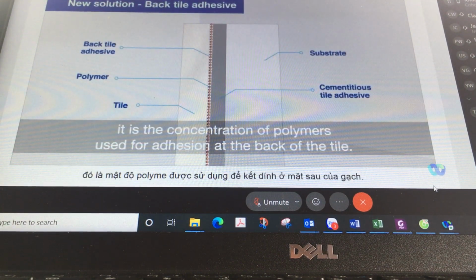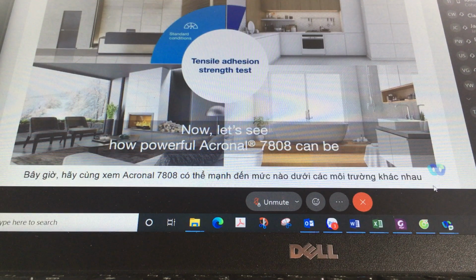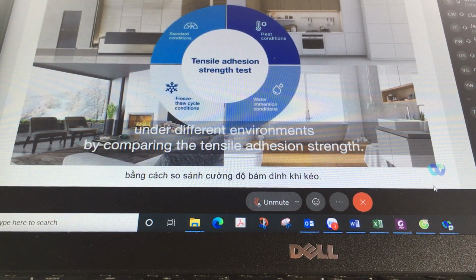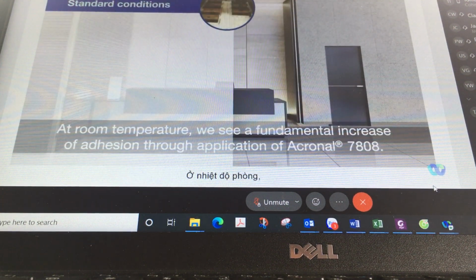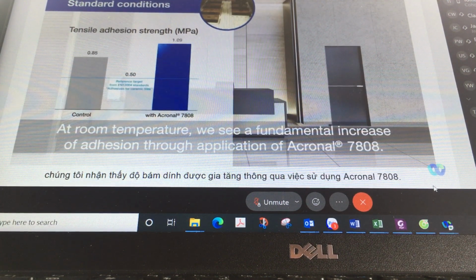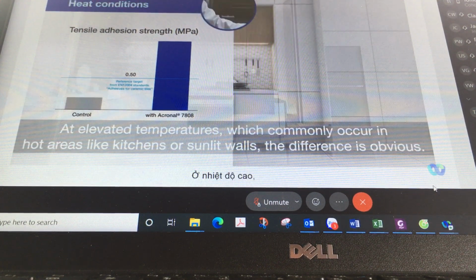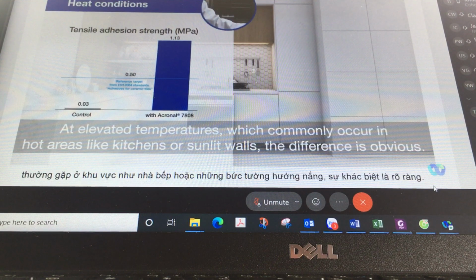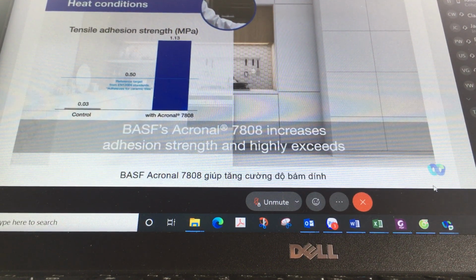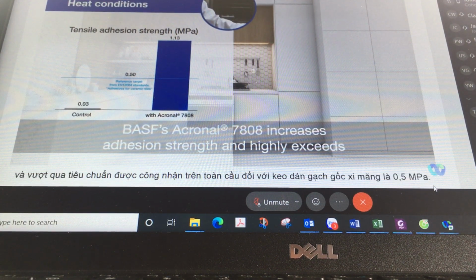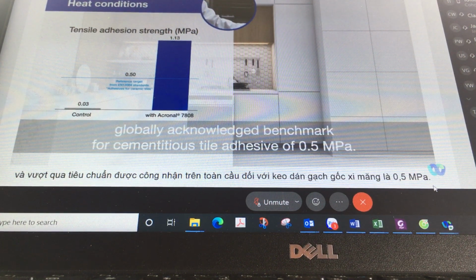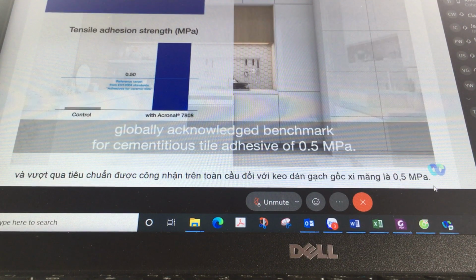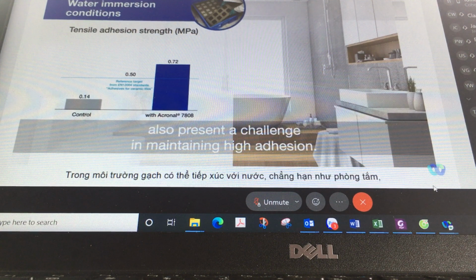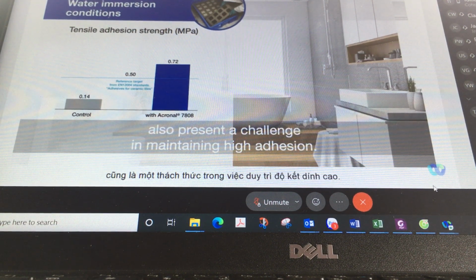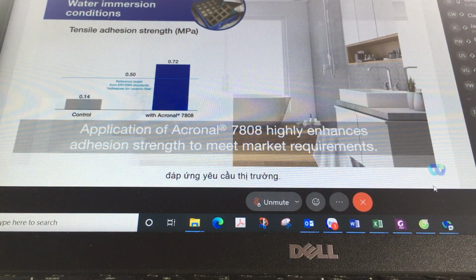As we explained earlier, it is the concentration of polymers used for adhesion at the back of the tile. Now let's see how powerful Acronal® 7808 can be under different environments by comparing the tensile adhesion strength. At room temperature, we see a fundamental increase of adhesion through application of Acronal® 7808. At elevated temperatures, which commonly occur in hot areas like kitchens or sunlit walls, the difference is obvious. BASF's Acronal® 7808 increases adhesion strength and highly exceeds the globally acknowledged benchmark for cementitious tile adhesive of 0.5 megapascal. Tiles subject to contact with water, such as in bathrooms, also present a challenge in maintaining high adhesion. Application of Acronal® 7808 highly enhances adhesion strength to meet market requirements.